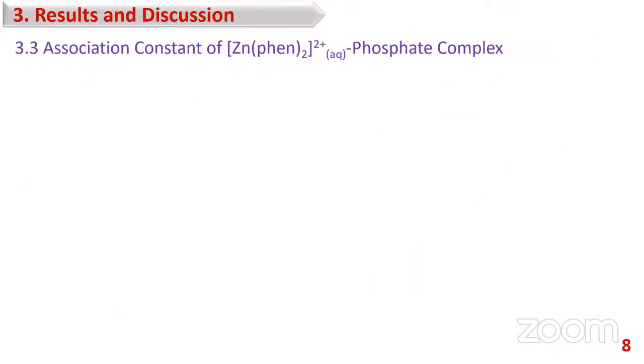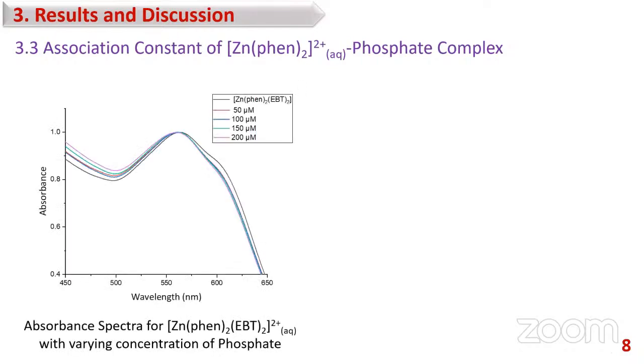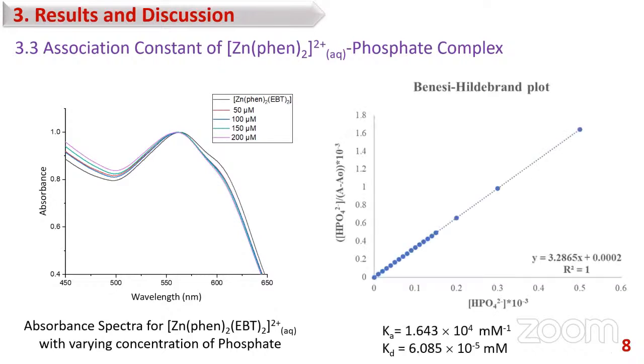In addition to that, the association constant of zinc phenanthroline to phosphate ions was determined. For this purpose, the absorbance spectra for zinc phenanthroline EBT complex with varying concentration of phosphate ions were plotted as shown in the graph. And some of the data were extracted from this graph to draw the Benesi-Hildebrand plot as shown here. The obtained association constant was 1.6 × 10^4 per millimolarity and the dissociation constant was 6.08 × 10^-5 millimolarity.